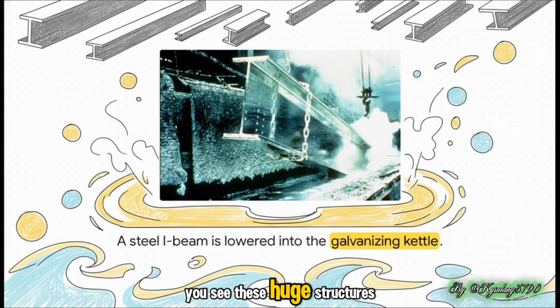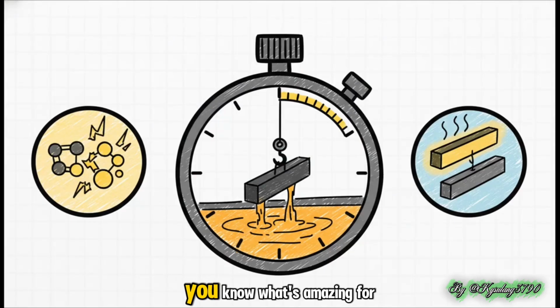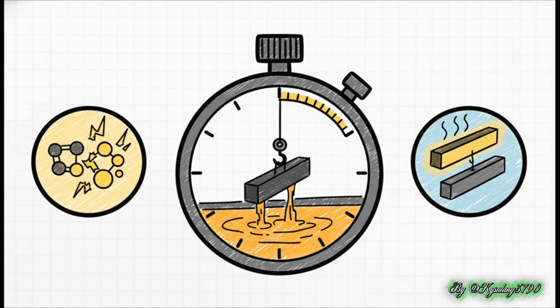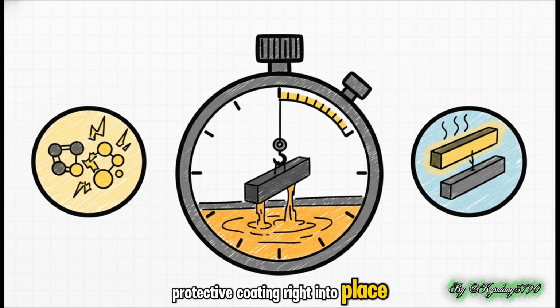You see these huge structures, like this I-beam, being carefully lowered right into the kettle. And that kettle is filled with at least 98% pure molten zinc. That's to make sure every single surface, every nook and cranny gets completely covered. You know what's amazing? For most things, this whole dip lasts less than 10 minutes. In that tiny window of time, the intense heat triggers a reaction that literally fuses the zinc to the steel. After it's pulled out, the piece is cooled down, and that locks the new protective coating right into place.